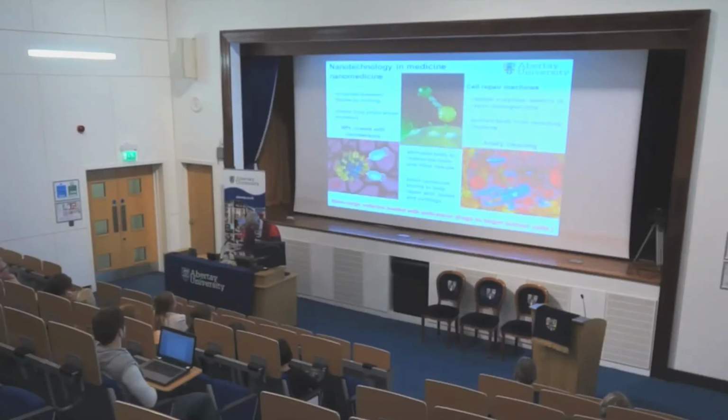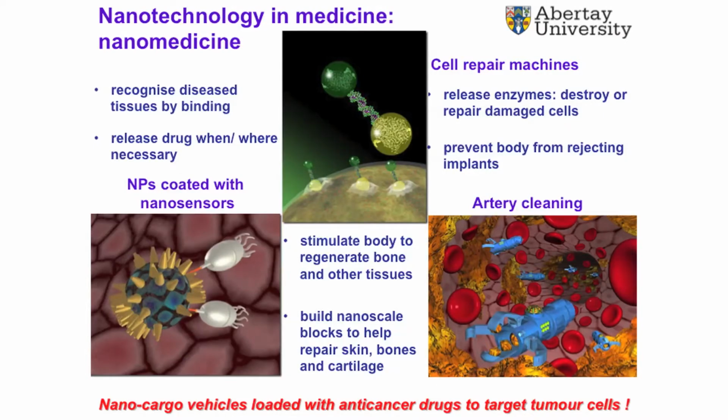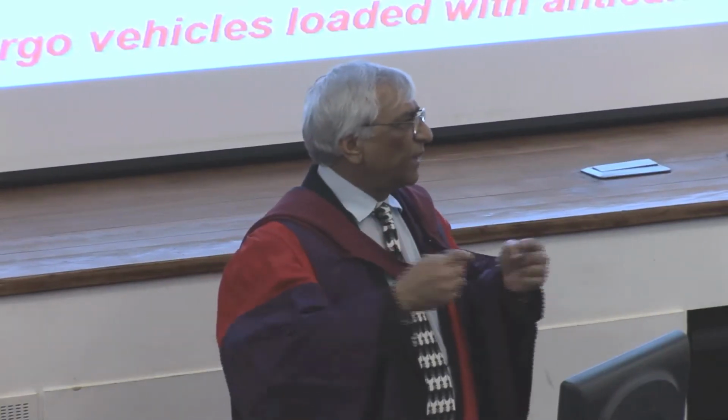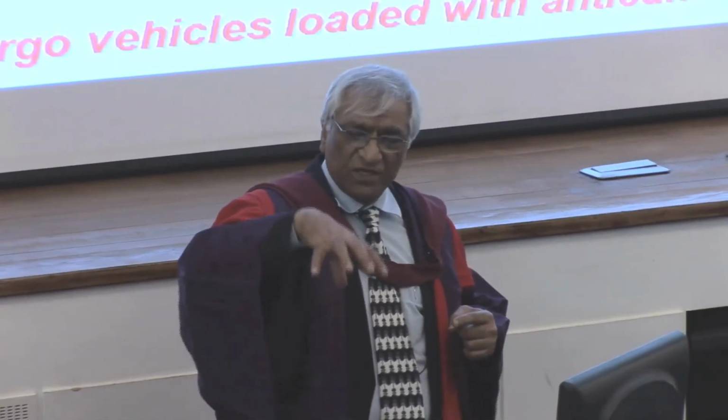Coming to medicine use, for example, you take gold nanoparticles, you can adjust the size so that it absorbs only infrared radiation or near infrared. And gold particles you coat with antibody to a disease. Say for example, you can take iron chloride, put some water, it makes iron hydroxide. Put some caustic soda, it gives iron oxide particles. Iron oxide is a magnetic particle, it is positively charged. Now the virus antibody has a negative charge that binds electrostatically. And on the other end of the AIDS virus antibodies, you can have the virus, because it is an antibody-antigen interaction. And then magnetic particles are floating with all the AIDS virus accumulated. You can just fish them out.